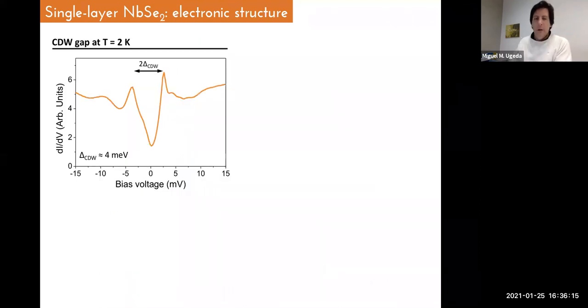Okay, so if we look now in more detail around the Fermi level, where usually there should be hallmarks of these many-body states, such as a charge density wave, for example, at 2 Kelvin, you can clearly distinguish the charge density wave gap. The width of this pseudogap is around 4 millielectron volts, which is in good agreement with the critical temperature that we found, which is 33 Kelvin. So nothing changes with respect to bulk.